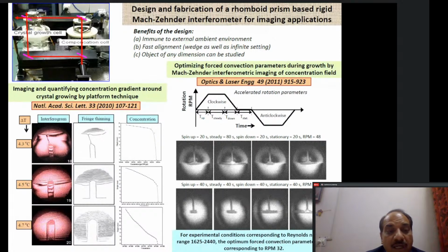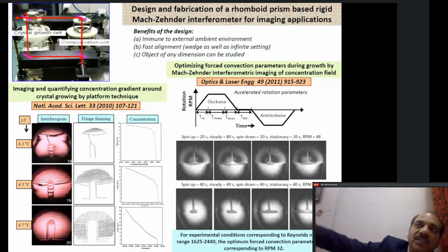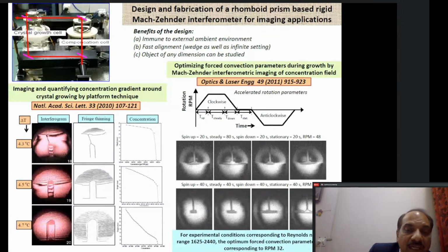If the crystal grown under certain conditions is bad, then online itself, while the crystal is growing, these are the images which we see directly on the screen. So if a crystal is growing for 30 days, we see whatever is happening inside the chamber on a screen continuously. Whenever we see that the crystal is picking up inclusions, we immediately go and change the temperature profile. We either increase the cooling rate or decrease the cooling rate, or for some time, maybe a few hours, we make the temperature constant so that there is no growth.